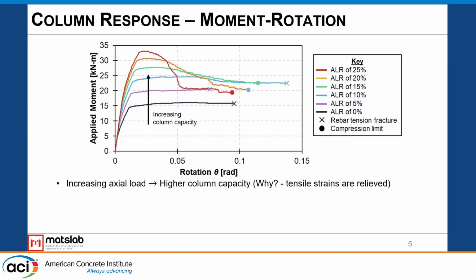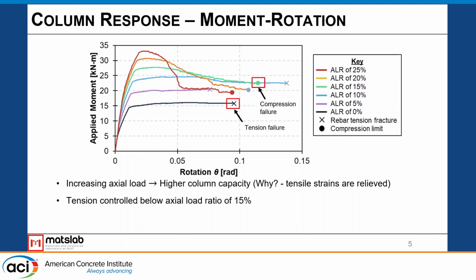In addition to the increased capacity, we can also observe the failure mode of these columns. I've gone ahead and marked out the tension failure with the X and a dot for the compression failure. What we can see is that up to and just below 15% axial load, we actually have tension-controlled columns. And then from 15% axial load, we have compression-controlled columns.